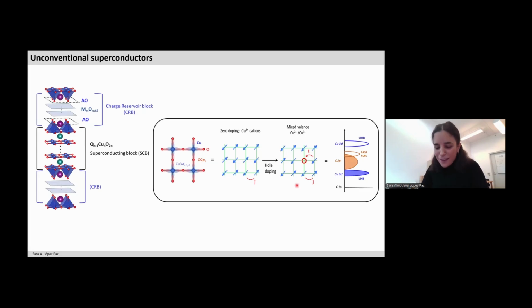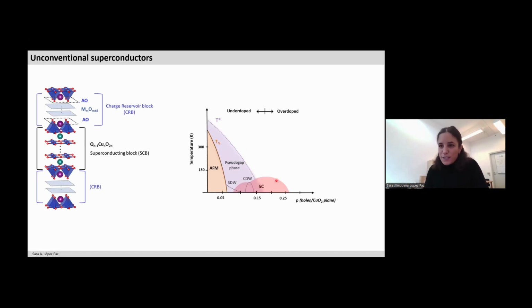Of course, one cannot forget the chemical picture, because actually these holes are not at the copper atoms, but are oxygen holes. But still this simplification works exceedingly well, because by considering only this hole doping level as the main factor for superconductivity to emerge, we can systematize most of the physical properties of these materials. And we see how, as a function of this hole doping level, we have a complex coexistence of several electronic phases which compete or precede each other. But at the time I was approaching this topic, we realized that most of the work was focused on this low doping region, whereas the highly doped region remained virtually unexplored.